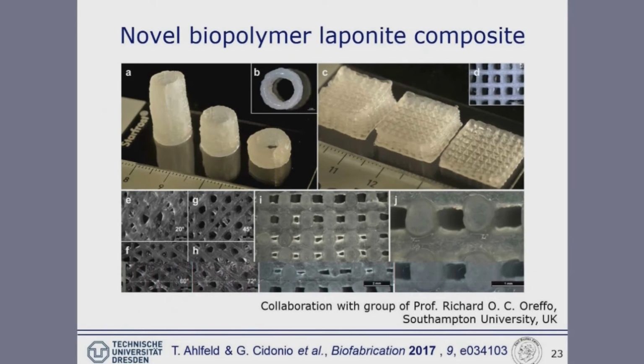Due to time limitations, I only want to show you a few photographs of scaffolds we have printed out of this composite material. These are open-standing hollow tubes, again printed in air. And I want to point out especially photograph J. This is a photograph from the side, and therefore you can see that we have open pores even from the side, which is not possible with a blend consisting only of alginate and methylcellulose.